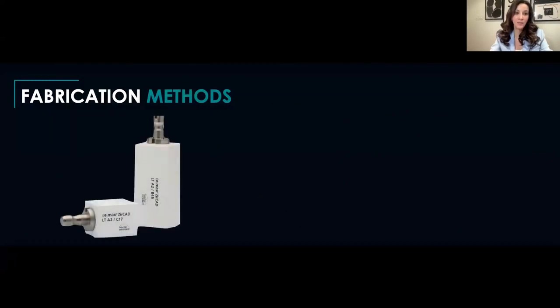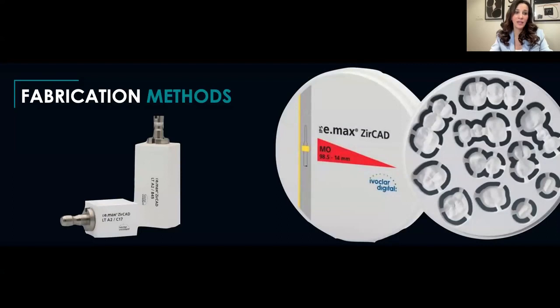And the fabrication methods, unlike our particle filled glass, you can't press zirconia. So it's really milled, and it could be milled out of chairside blocks or larger pucks. There is now a lot more research coming out about printing zirconia. So that's going to be more readily available, where we can have printed materials made out of zirconium dioxide. So stay tuned for more information about that.